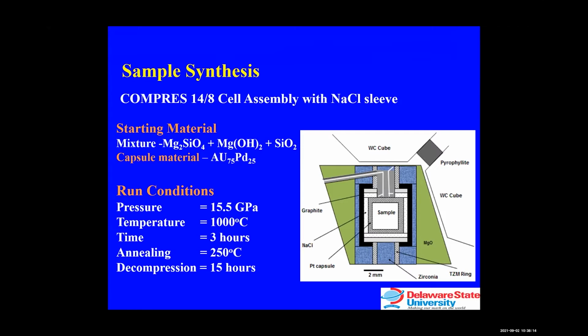So for hot pressing the wadsleyite sample, the starting material is forsterite, with brucite to introduce water into the sample, and then charge balance by adding silica. When we started with a mixture of MgO, silica, and brucite, we ended up with mixed phases because phase E and others are very sensitive to temperature. So this was the best way to proceed. We also use a gold palladium capsule to minimize water loss, but sometimes we just use a platinum capsule because it's easy to extract the sample, hot pressed inside a platinum because it's relatively soft.